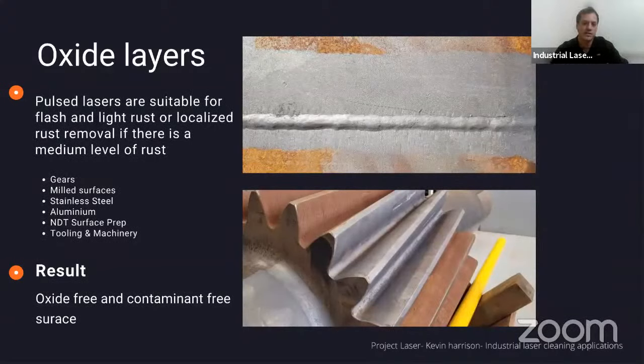Target thin layers of corrosion, so flash rusting, light rust, or localized paint corrosion removal. Some examples of that are gears and pinions, which you see on the bottom right, milled surfaces, stainless steel and aluminium, which naturally have very thin layers of oxides, NDT surface prep, as well as tooling and machinery cleaning. When you clean those surfaces and use good quality extraction, you end up with a very clean surface that's ready for anti-corrosion treatment or a paint coating. It's always imperative, if you're removing corrosion, that you're also extracting away the particles, because otherwise you're just getting oxide going up in the air and falling back onto your item, and it's just going to corrode again. So you need to have good quality extraction when you're cleaning steel. You go to the next one.